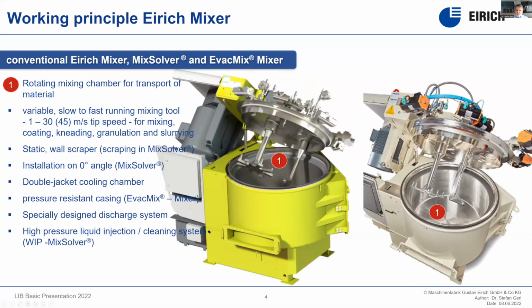As I mentioned, we have a rotating mixing chamber, which is taking care of the transportation of the material. If we have a static mixing chamber, like in a planetary mixer, the mixing tool has typically two tasks. First of all, transportation of the materials. Secondly, the mixing. If you increase the speed of the tool, then typically the transportation collapses, because by centrifugal forces, everything is pushed to the outside. This means typically these kinds of machines with static mixing chambers have to run at a reasonably low speed, which is not good enough to disperse and dissolve fine additives like carbon black or nanoparticles. So at the end, they need a second dispersing tool to do this job.